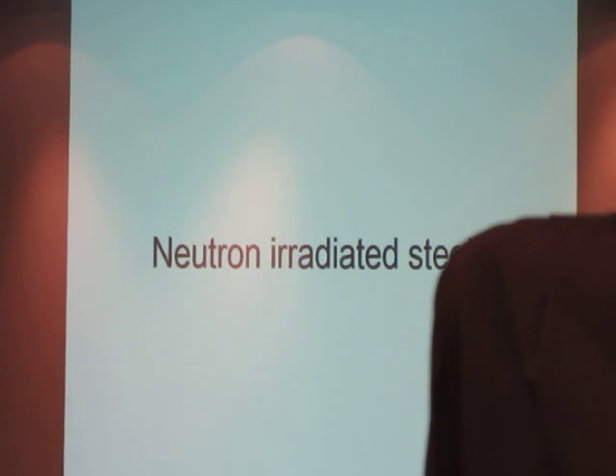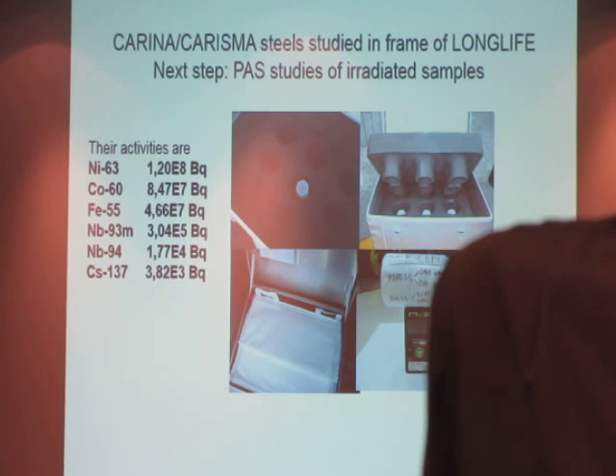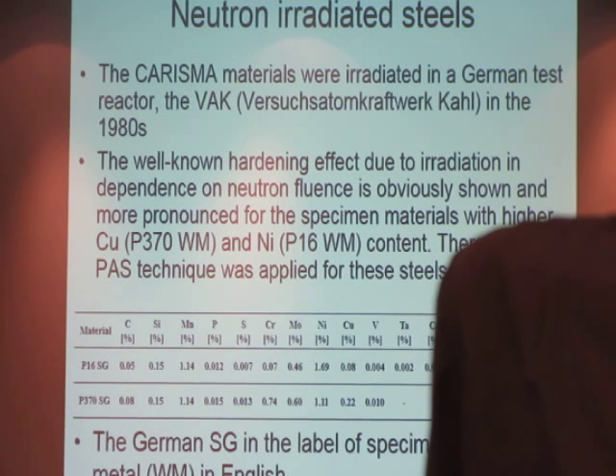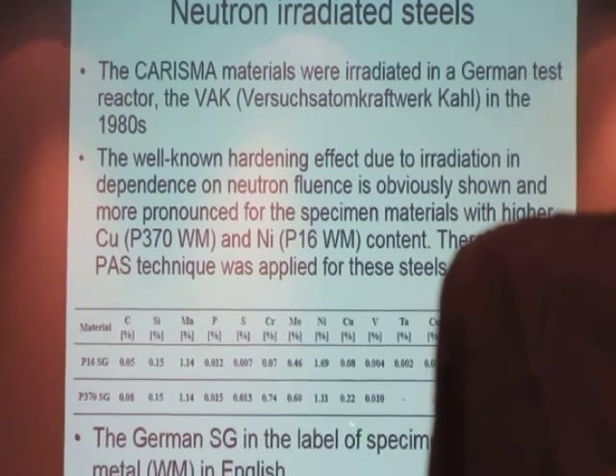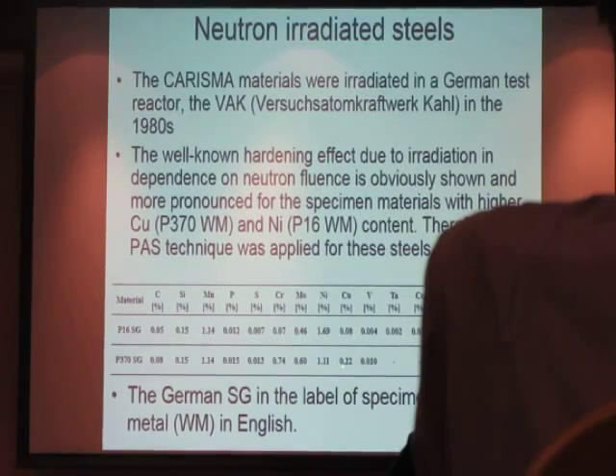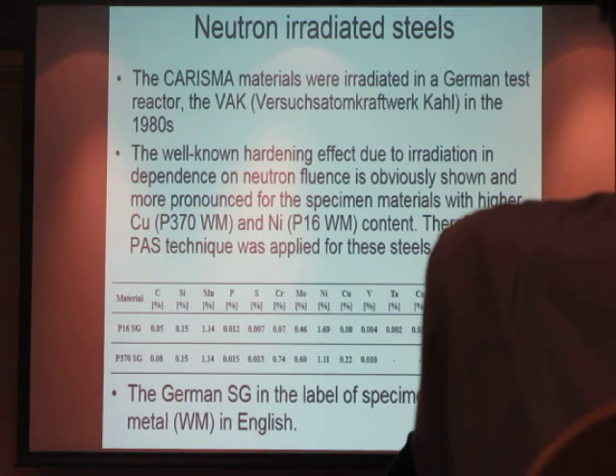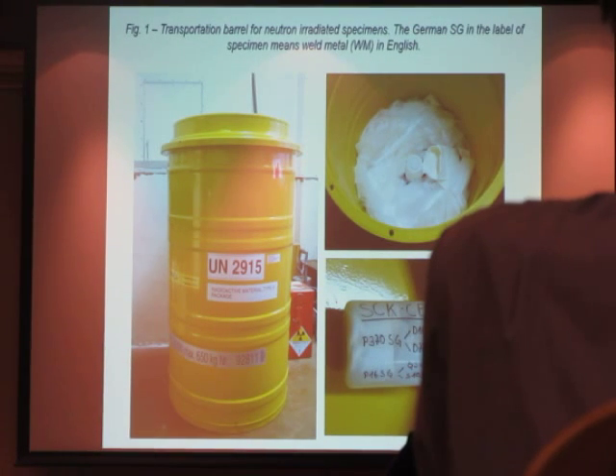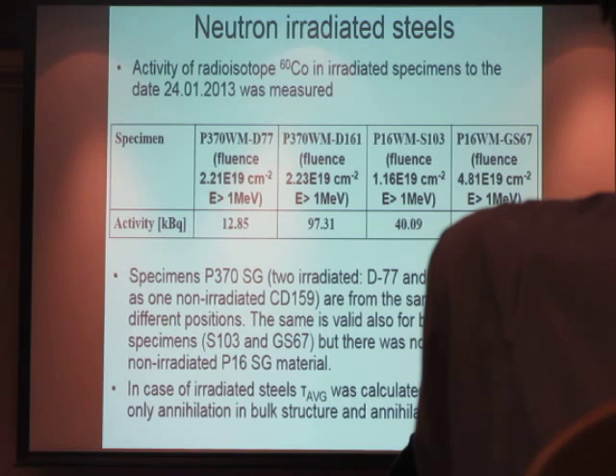Good. Neutron irradiated steels. These German steels from the Karlstein reactor were transported in the frame of the project Long Life, and we measured it as subcontractors for the Areva company. There is the chemical composition of the irradiated, mostly weld metal, Schweißgut in German, weld metal in English. And you see that the copper content was, let's say, at the limit, and 0.22 was the highest one from the past. Transport was a huge story. We needed a 200-liter barrel to transport it from Belgium to Slovakia. It took 2 years till the transport was accepted. Finally, the activity was not too high, but